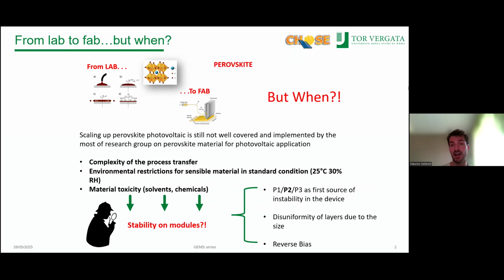And moreover, the stability of the device and of the modules especially, because the processes to get modules are more than to get a cell, obviously. For example, the P1, P2, P3 laser processes can be a first source of instability in the device if they are not well done, as well as the uniformity of all the layers on the larger substrate, due to the technique that we choose, which cannot be directly transferred from the spin coating process to eventually blade coating, slot die coating, or inkjet printing, for example. Another source of instability for the modules could be the reverse bias, in this case when we put more cells in series connection.